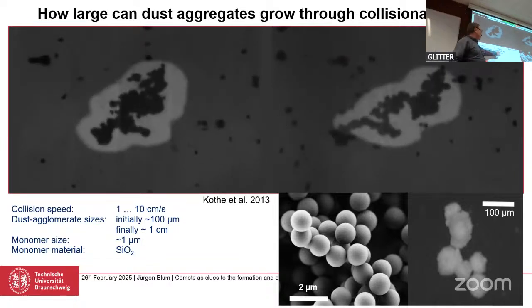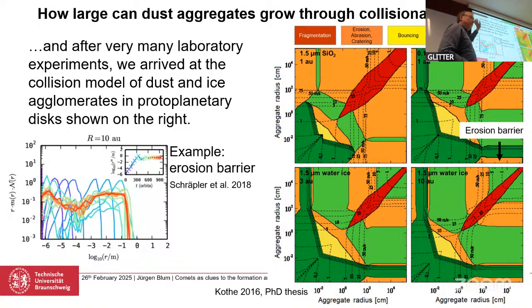So again, originally the clumps were 100 microns, consisting of micron grains. Silica is the material here. And finally, we achieved centimeter particles. We did literally hundreds of those types of experiments and different ones. And in the end, after really many, many experiments and decades of work, we ended up with a dust collision model, which is very complicated, as you can see here.